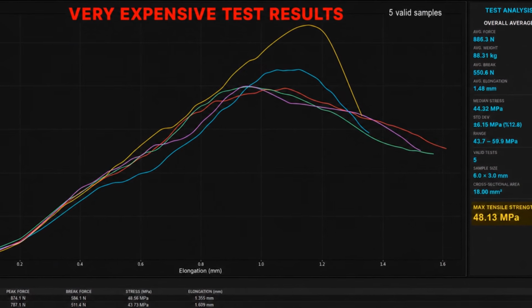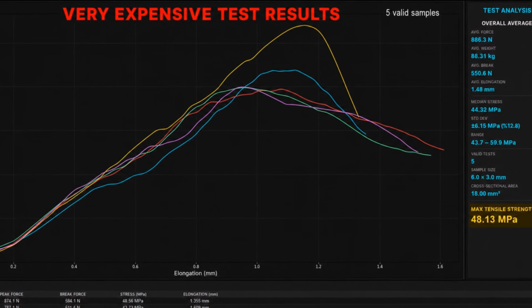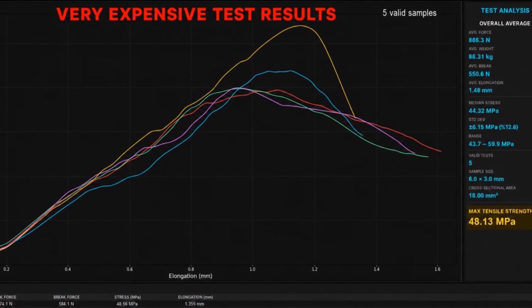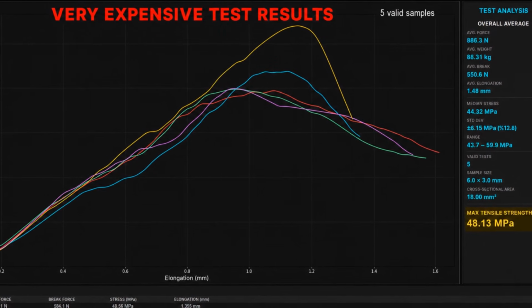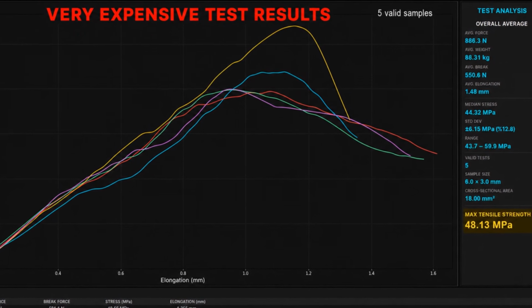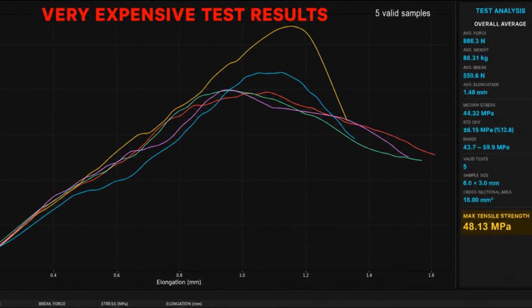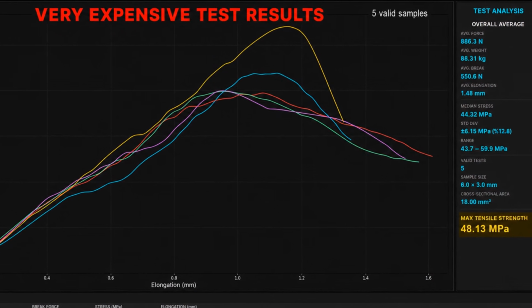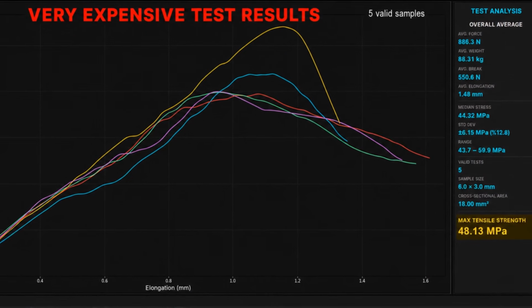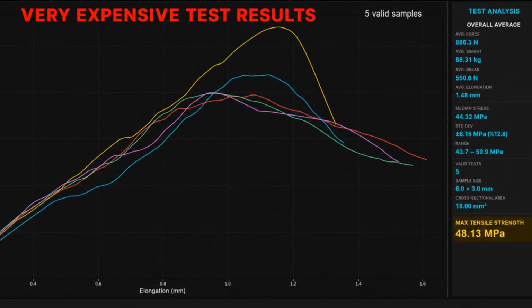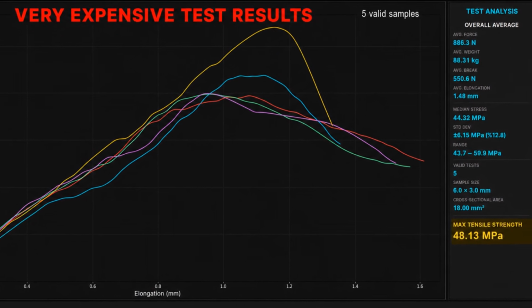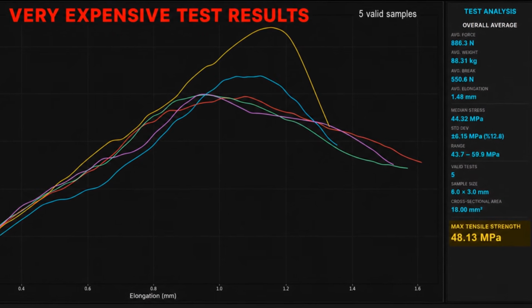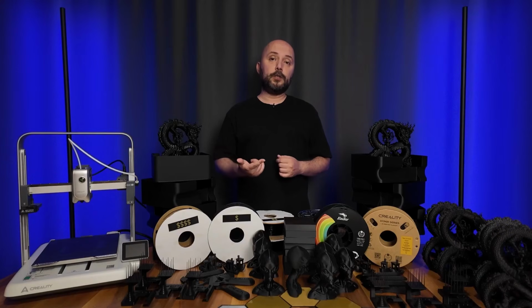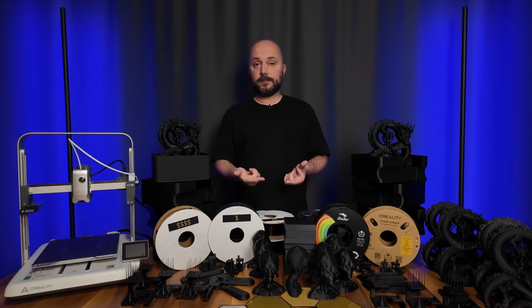I won't go over each of these one by one, because in my opinion there are two important points. One of them is already the direct result of the tensile break test. That is the megapascal value written at the very bottom. As you can see, the very expensive filament reached a value of 48.13 megapascals, and after this force was applied, the break occurred. Before breaking, it stretched by 1.48 millimeters. The megapascal value here shows the tensile strength of the material. Of course, this is based on the test piece we made.